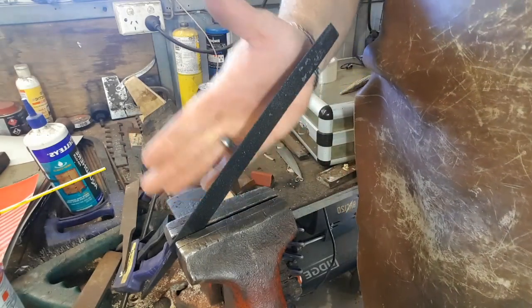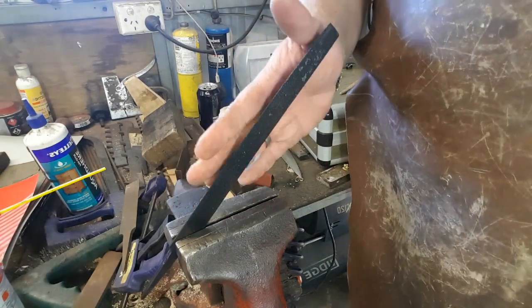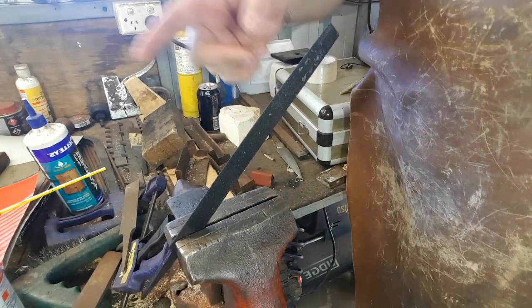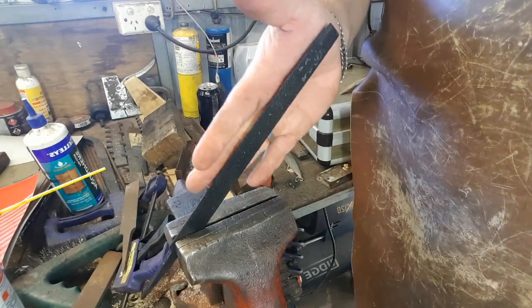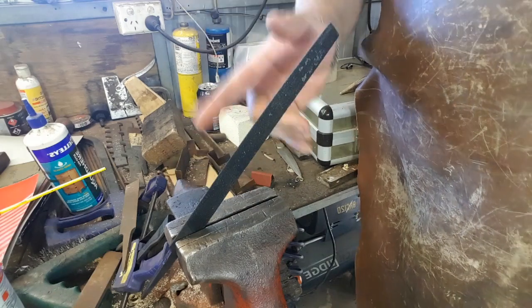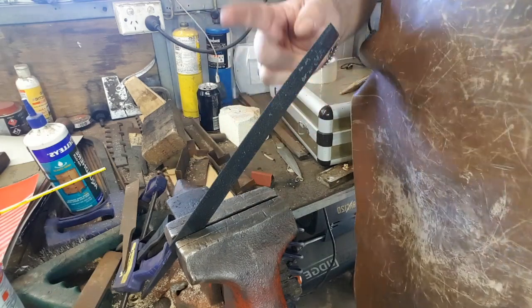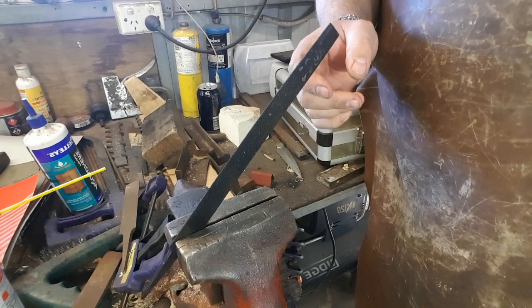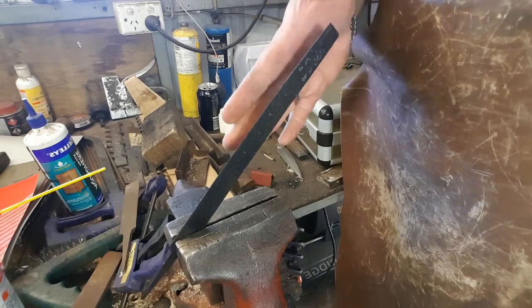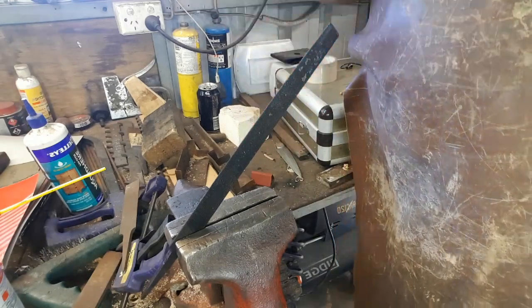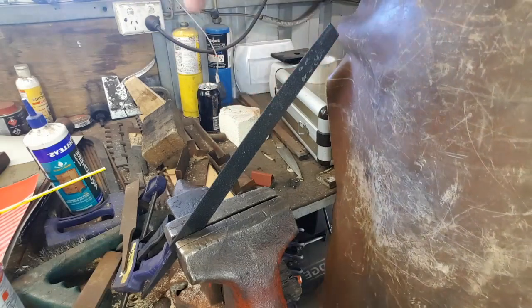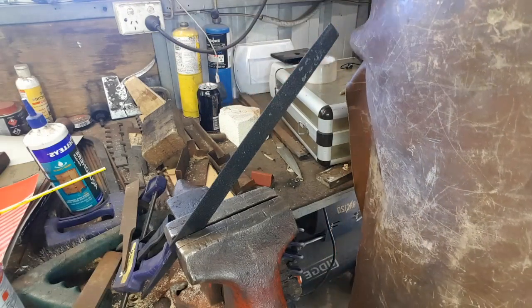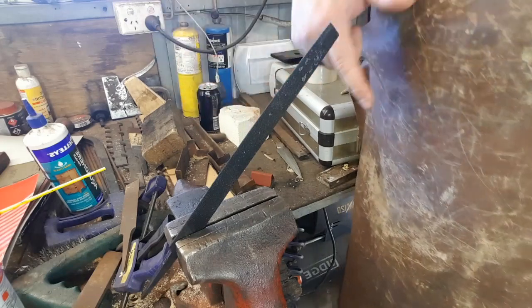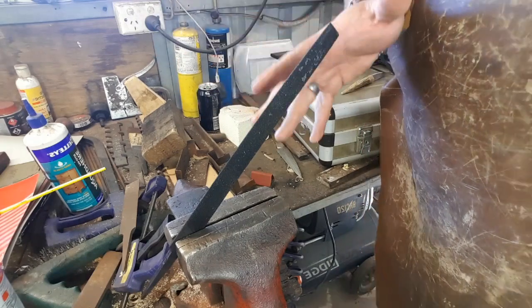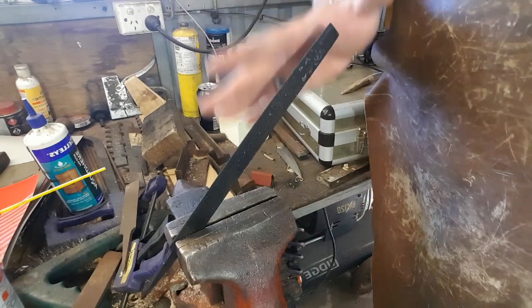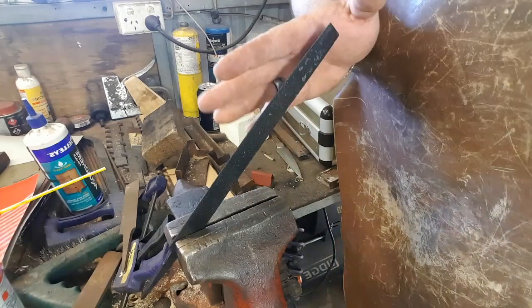And the important thing is, this is only like 20 seconds after the quench. I've just moved the camera. But it is already cool enough that I can touch it. The reason for that is because I let the steel cool down to oil temperature inside the oil bath. Now, if I wanted to tweak this, I could have, if I'd only quenched for about 4 to 6 seconds, and then done some tweaking outside of the forge and then gone back into the oil. That's a more advanced technique. In this case, we're just going straight from the quench to testing for hardness.